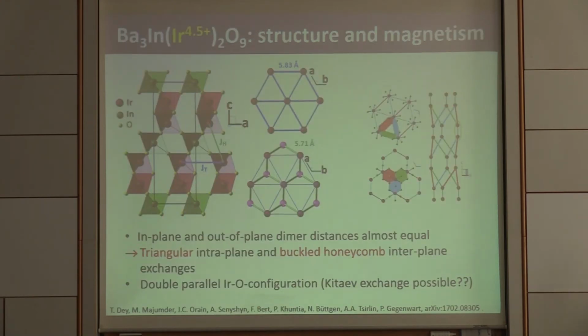So of course we now need to ask what are the exchange paths which could be realized in this material, and it's a bit more complicated compared to the layered honeycomb materials, because here we have almost equal distances between two iridium sites. In plane the distance is 5.83 angstrom, and they form a triangular lattice. Out of plane, the distance is even slightly shorter, 5.71 angstrom. And this out of plane connection, as indicated here, always involves three sites of the lower part of the bi-octahedra on the upper plane, and three respective sites of the upper bi-octahedra of the lower plane. So we have here an effective buckled honeycomb lattice.